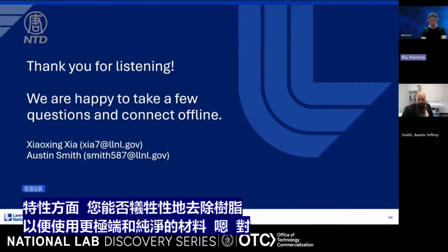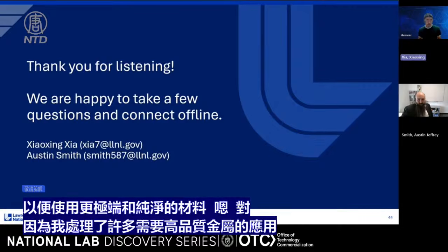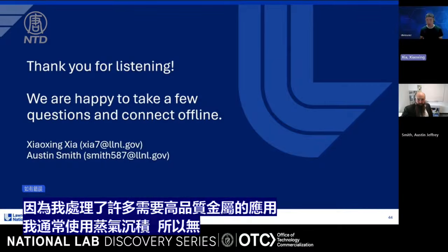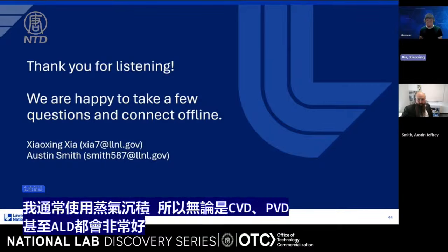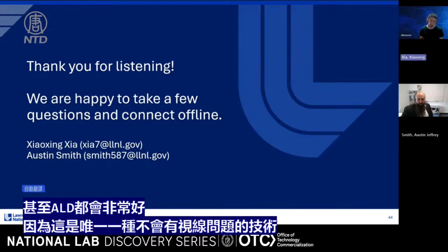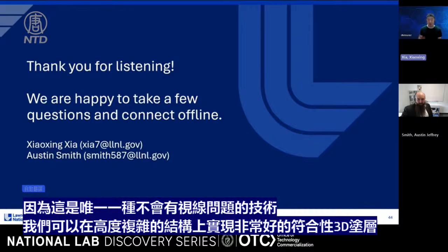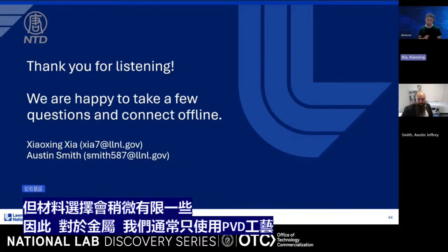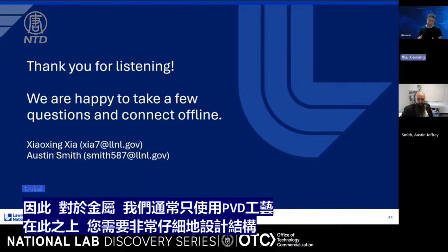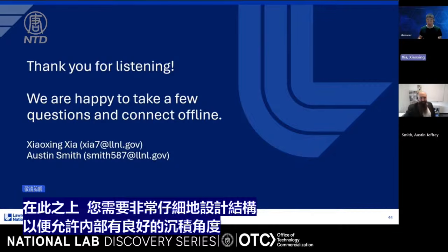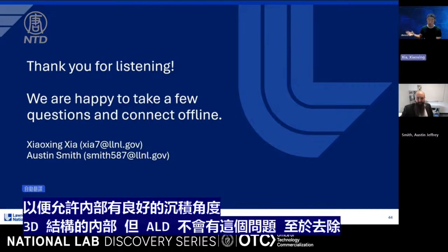Right. Because I deal with a lot of applications that require high quality metal, I normally use vapor deposition, so either CVD, PVD, or ALD. ALD would be very nice because that's the only technique that doesn't have a line of sight issue. We can have very nice conformal 3D coating into highly complex structures, but the material choice is a little bit more limited. So for metal, we generally use just PVD processes. On top of that, you have to design the structure very carefully to allow angles for very nice deposition onto the inside of 3D structures. But ALD wouldn't have this issue.